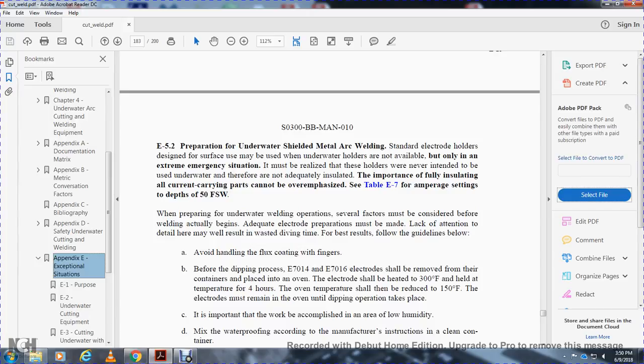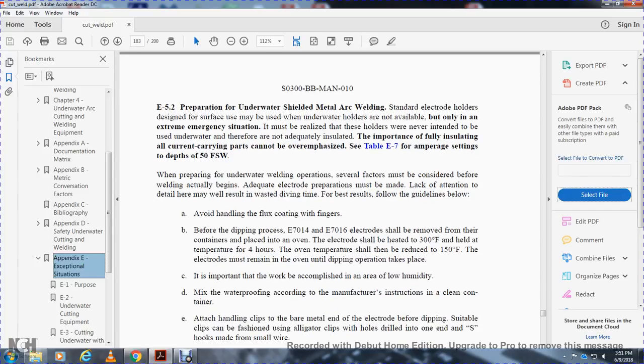E52, preparation for underwater shielded metal arc welding. Standard surface electrode holders may be used when underwater holders are not available, but only in an extreme situation. It must be realized that these holders are never intended to be used underwater, and therefore they are not adequately insulated. The importance of fully insulating the current carrying parts cannot be overemphasized. Table E7 gives amperage settings at depths of 50 feet in salt water.